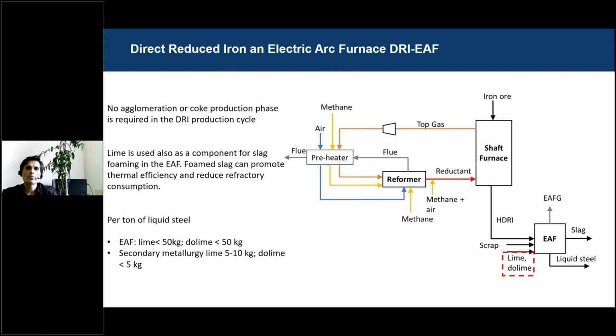The idea behind this alternative process is to remove the oxygen from the iron ore directly in a solid state. The solid product coming from these shaft furnaces is sent to the electric arc furnaces, where it is converted again into liquid steel and then into secondary metallurgy. Here, conversely to the BF-BOF cycle, in the DRI-EAF there is no need of sintered material, so this process is inherently efficient compared to the BF-BOF, but we still need lime again to protect the inner part of electric arc furnaces, but also to form a kind of foamed slag to prevent the damage of the inner part, but also to protect the liquid steel from the atmosphere. So lime plays a key role also in this case.